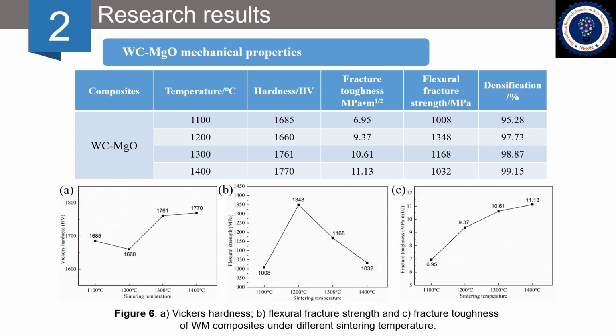Conversely, the fracture strength increased from 1,008 to 1,348 at first, and then decreased to 1,032 observably. The highest value of fracture strength was achieved when the sintering temperature reached 1,200 degrees. Fracture strength relied on hardness and fracture toughness when the pores were eager and microstructure had a major impact.